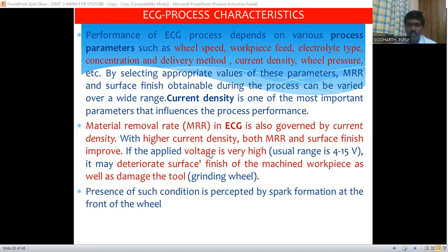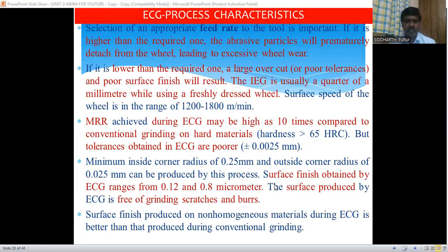Coming to the voltage, if the applied voltage is very high, usually the range is between 4 to 15 volts. If we supply more than this, it may reduce or damage the surface finish of the machined workpiece, as well as damage the tool, that is, the grinding wheel. So we have to maintain the voltage between 4 to 15 volts. The presence of such conditions is perceived by spark formation at the front of the wheel. If your voltage is more than 15 volts, a spark will be developed, and because of that spark, damage to the tool or the workpiece may take place.